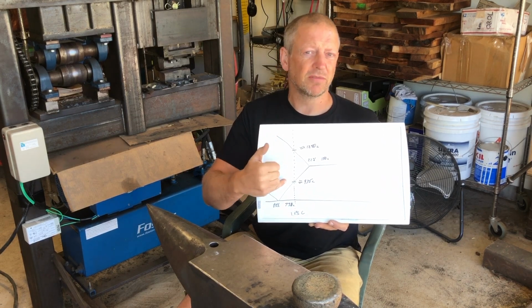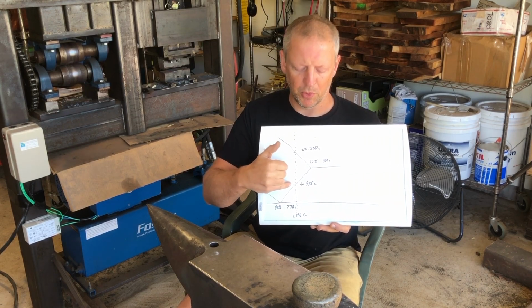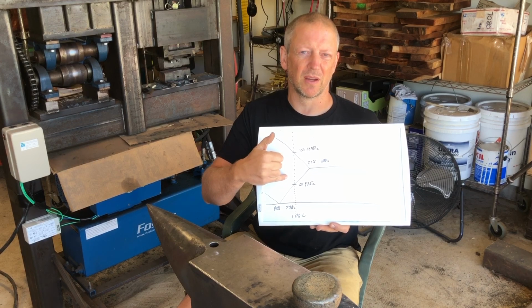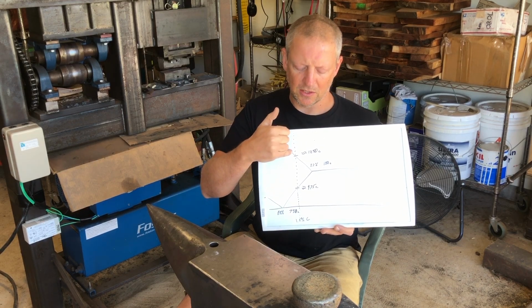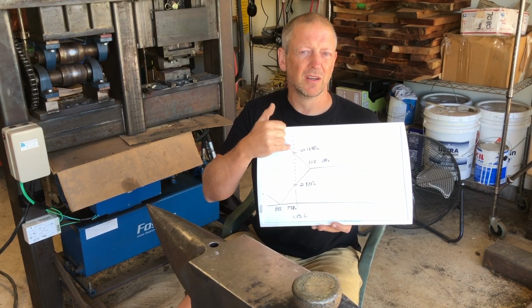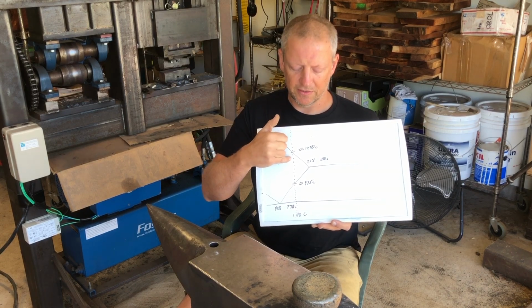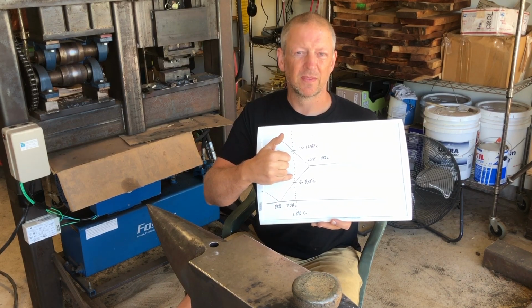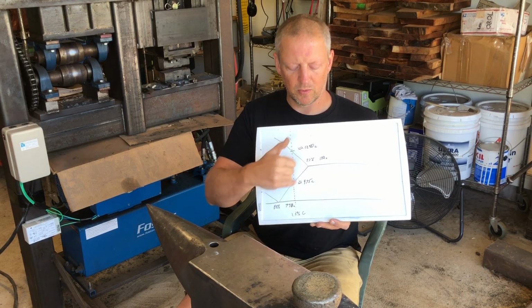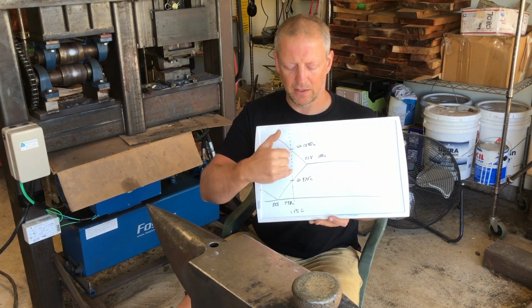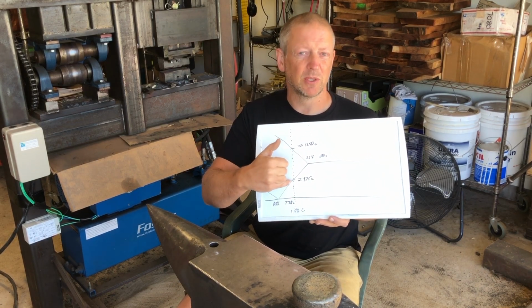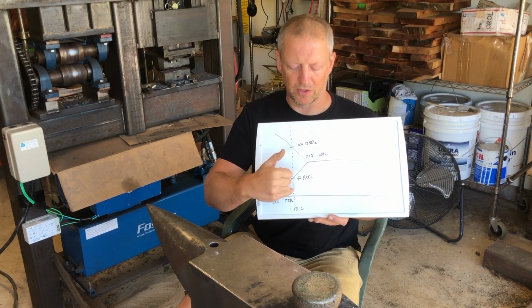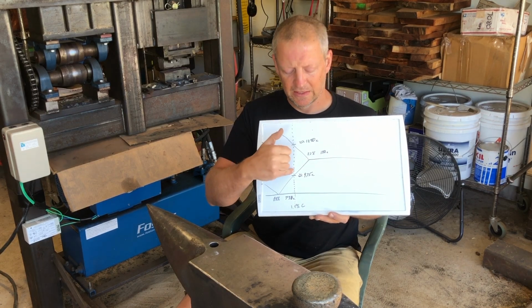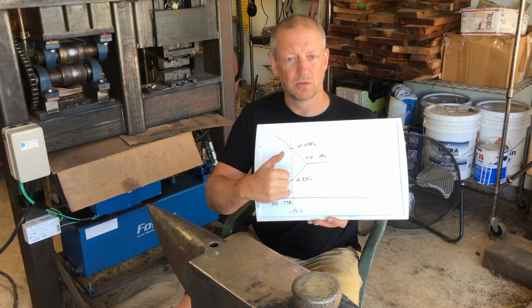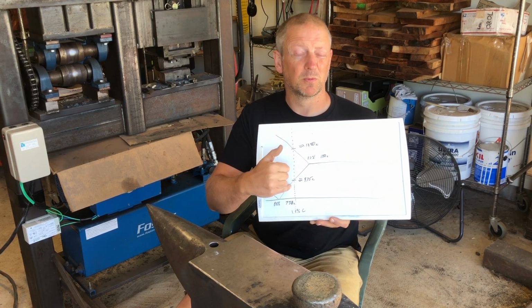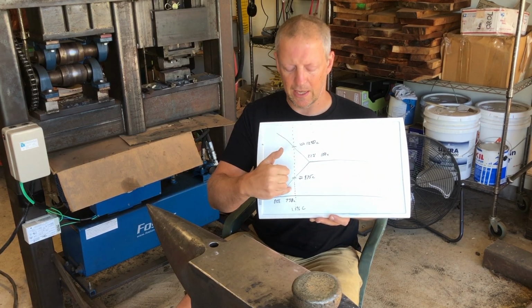carbides are dissolving. We are above the temperature where they are really stable. And so those primary carbides are actively dissolving as we come down. And then when we hit the ACM line, carbides are now stable. We're now in a temperature range where those carbides are actually stable, and we begin to precipitate carbide again.